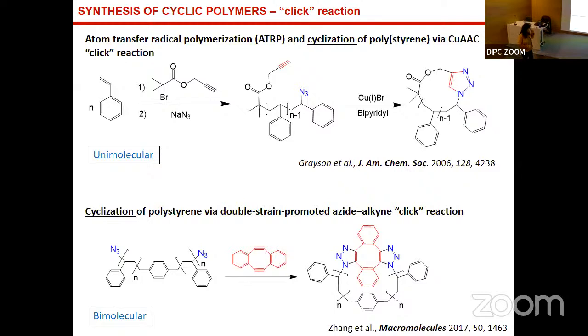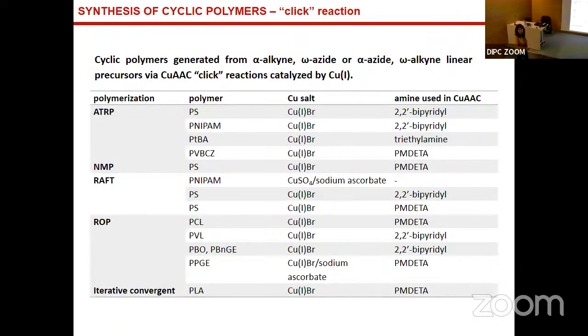Then, well, there are many examples in the literature after this first example of the use of click chemistry, but I brought this one here because in this synthesis, they demonstrated that with the use of strain-promoted azide-alkyne click reaction, the use of metal catalysts can be avoided, which is probably good for biological applications, when we don't need to use a metal catalyst. This is an example of bimolecular reaction. This occurs also very fast, and there are many examples. For example, it's a table with plenty of examples found from the literature where different kinds of polymers, polystyrene, EPAN, butyl acrylates, etc., can be synthesized by different polymerization techniques, and using the copper catalyzed azide-alkyne reaction can generate these cyclic polymers.